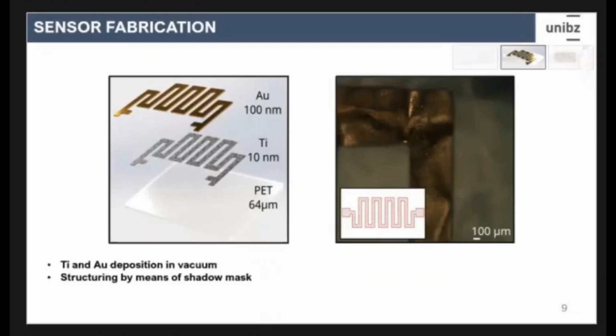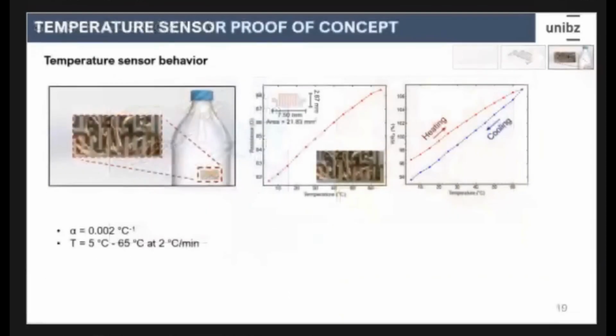Here we see the structure that was given to the temperature sensor, and a micrograph of one small area of the sensor, indicating that the warpage in the surface was not that significant for function. Here we see the idea that we had, to put it in a bottle to measure the temperature of the liquid inside. But before that, we tested it in an environmental chamber, and we see a fairly linear curve, where we went from 5 degrees Celsius to 65 degrees Celsius at 2 degrees per minute to calculate the temperature coefficient of resistance, which turned out to be 0.002. We also detected some hysteresis when going from 5 to 65 and 65 to 5 again.